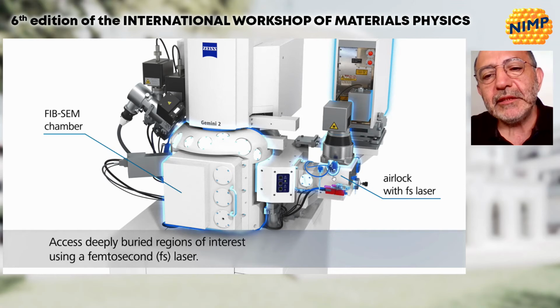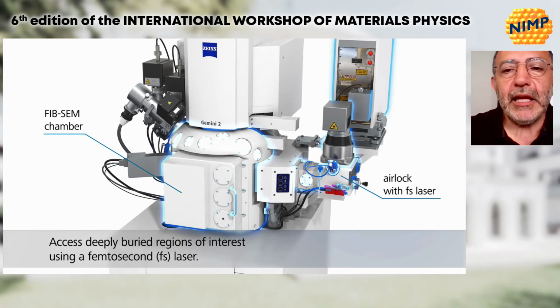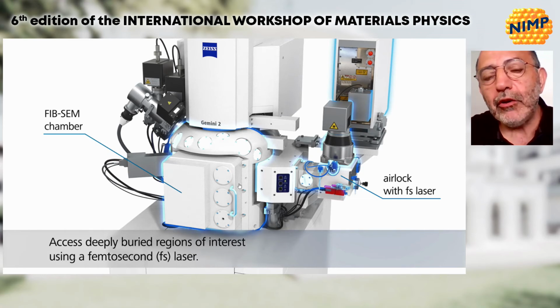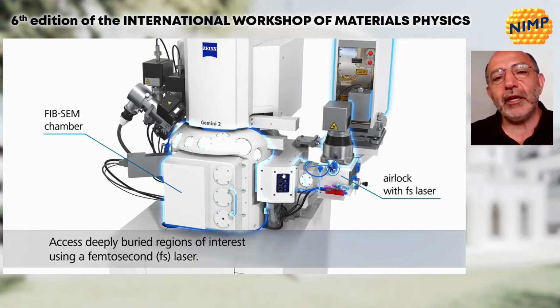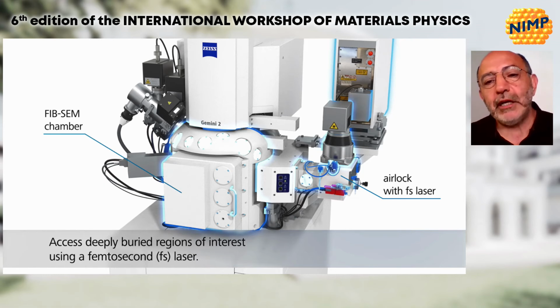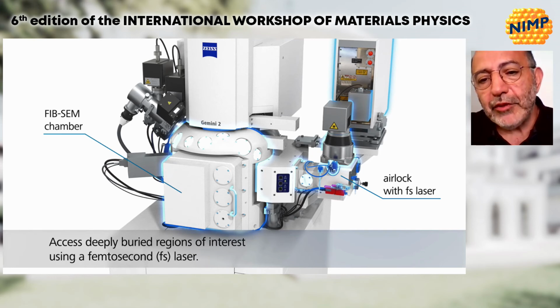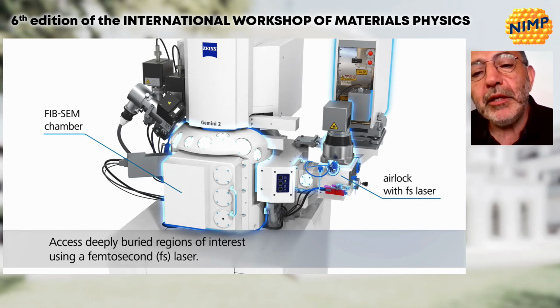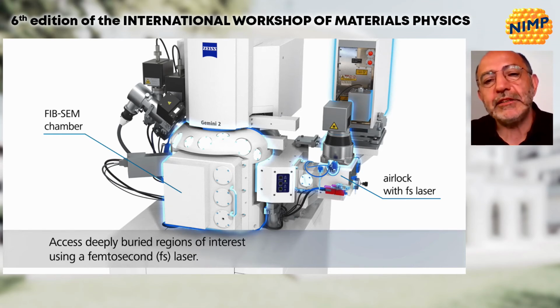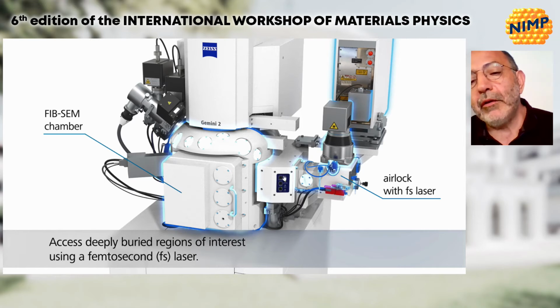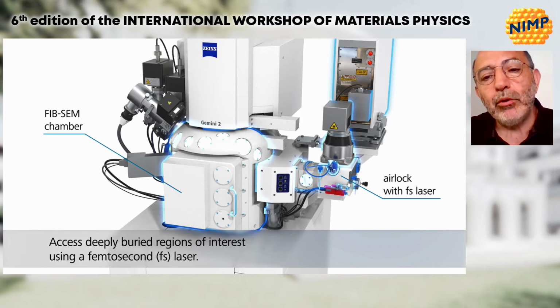The most important part is that the laser system is decoupled from the chamber of the microscope. It has its own vacuum chamber interconnected via an airlock, and you can shuttle the samples between both chambers because both chambers have the same coordinate system. You can move the samples back and forth between laser and FIB, or laser and electron microscope, mass spectrometer, without losing your coordinates. The second most important part is, you can imagine, if you are cutting a few cubic millimeters of sample, you produce a lot of debris of material, which would produce a lot of contamination in the microscope. That is the reason why we use a separate vacuum chamber, interconnected with the microscope via an airlock.